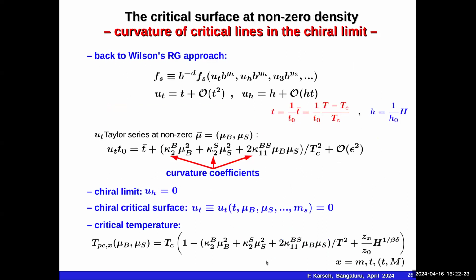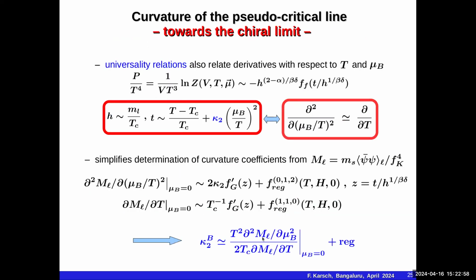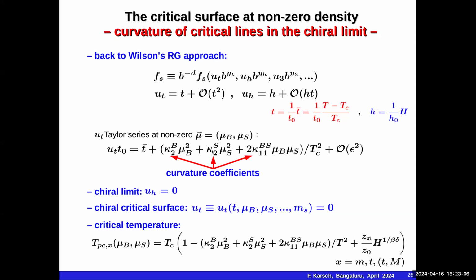And one can go on and generalize this not only to baryon chemical potentials, but also to strangeness chemical potentials. So when I look at the dependence of the temperature-like variable in the scaling fields, then it depends on baryon chemical potentials, strangeness chemical potentials, and certain mixed terms. All of them come with an expansion coefficient that can be calculated similarly to what I said here for the curvature coefficient in baryon chemical potential direction, so that I can do also for strangeness direction and for these mixed directions. And that allows me then to define the variation of the pseudocritical temperatures with various chemical potentials.